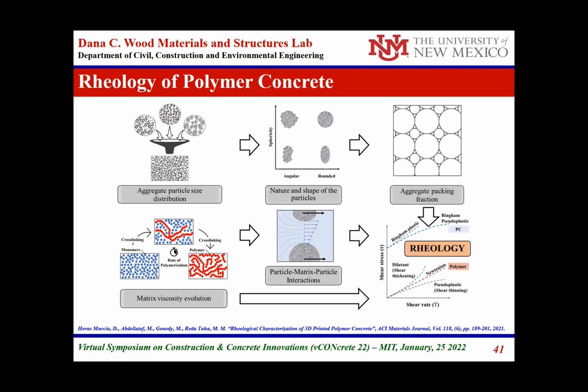And here the change that happens to develop the static yield stress is the cross-linking that occurs in the polymer, which results in the material being able to withstand higher stresses. We evaluated both the rheology of the polymer and the rheology of the polymer concrete.